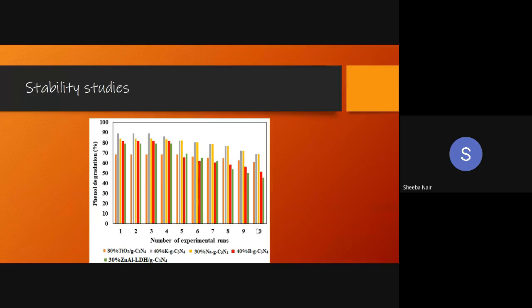Number of experimental runs means number of times that you are repeating the experiments. With the 10th experiment itself, mind you, it is not the 100th experiment, the degradation had come down drastically. You can see, this is your layer double hydroxide 30%. Layer double hydroxide doped with the graphitic nitride, the phenol degradation was only around 45% with only the 10th experimental one. So this is the problem with the real industry system. So we have mimicked an industrial effluent, we have mimicked an industrial setup for our studies.